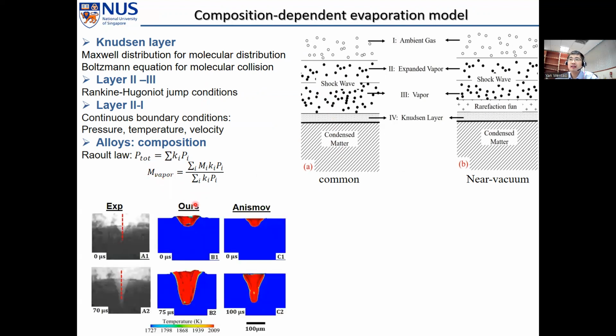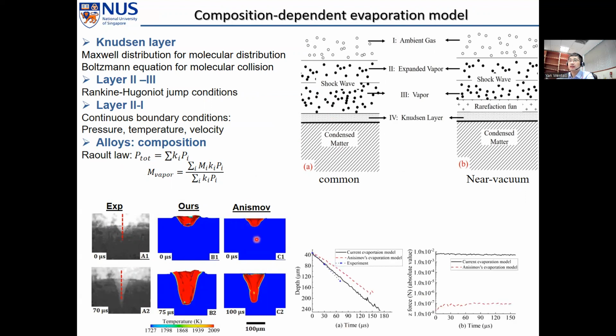And then we validate our model against the in situ X-ray imaging results by Argonne National Lab. Now you can see these are similar results using our own evaporation model, and this is a traditional evaporation model developed by Anisimov in the 1970s. So you can see the difference in the development of the keyhole.